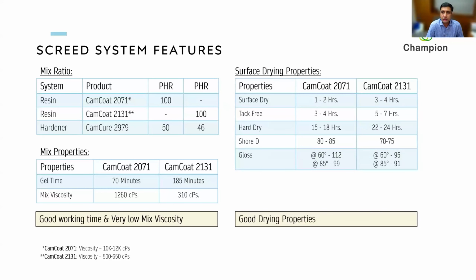We've also checked the surface drying properties, and you will notice that it's a very quick dry system, within 1 to 2 hours when used with a basic liquid resin, or 3 to 4 hours when used with a low viscosity resin. And it can give a hard dry in 15 to 18 hours or 22 to 24 hours, which is very much desirable for a screed. And also the hardness is very high, showing that it is a very hard system and would provide the strength required.